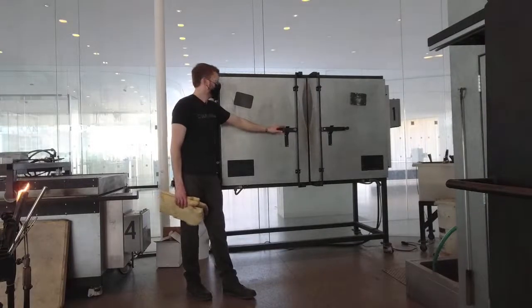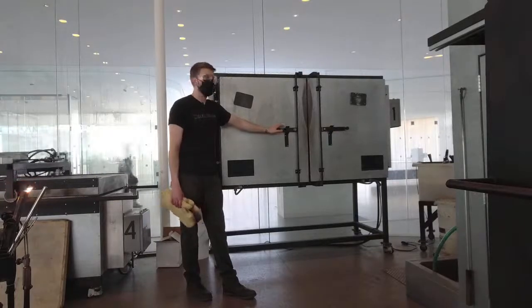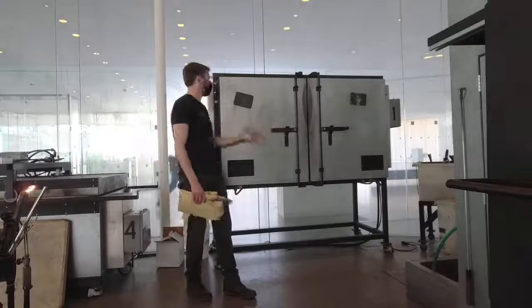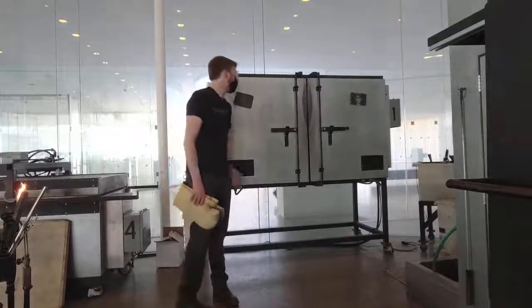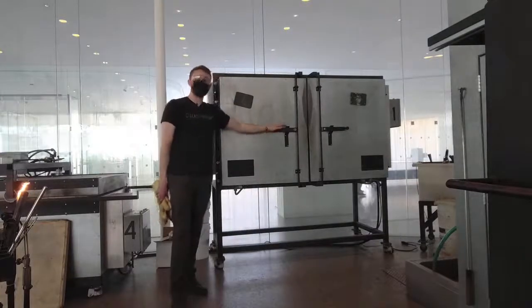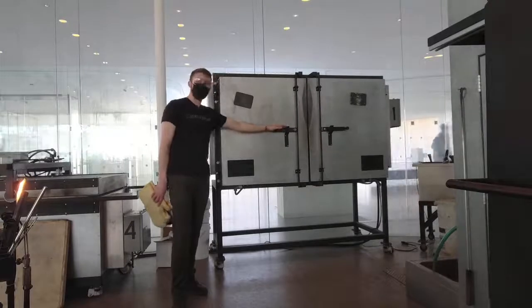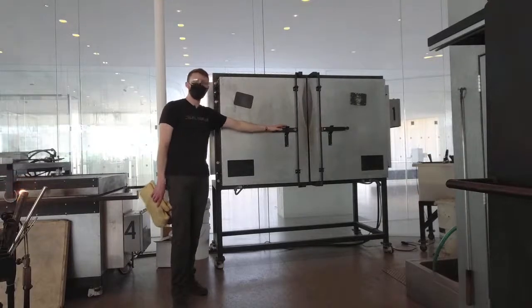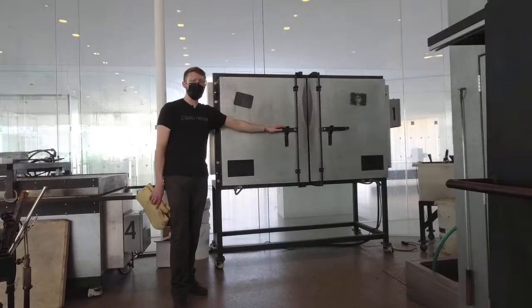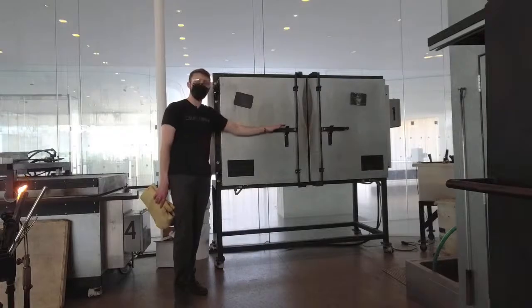So the glass was rigid, it was solid at that moment, but it's still about maybe 1,000 to 900 degrees. And at that temperature, the glass is stable to rest at. It's not too hot in this box at 918 to slump it, and it's not cold enough to induce any thermal shock. So it could rest in here for a couple days or a week, something like that, and it would go relatively unchanged. But we were going to get it out as soon as possible.